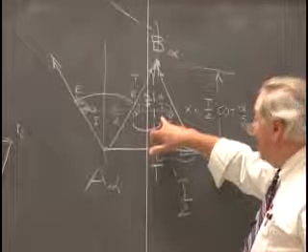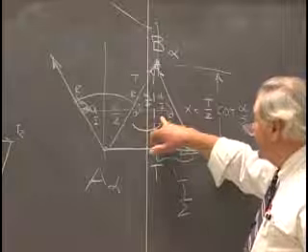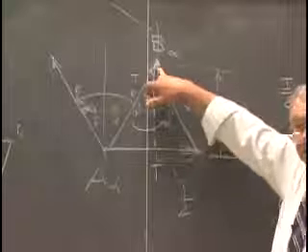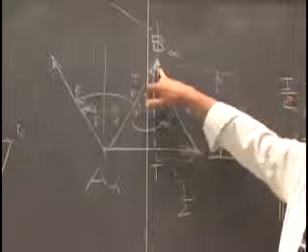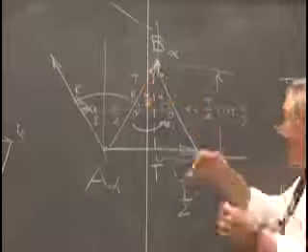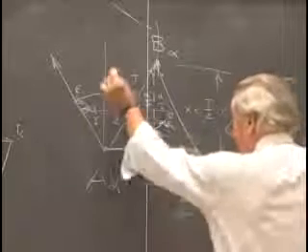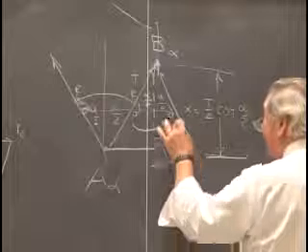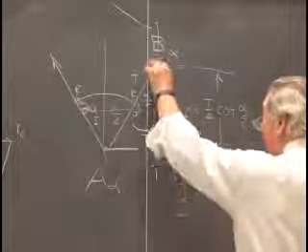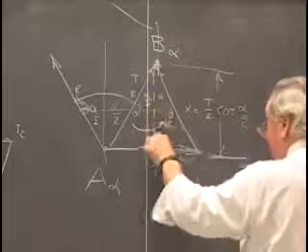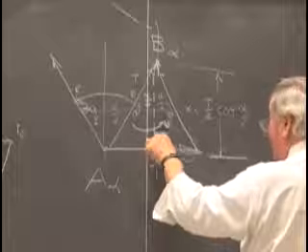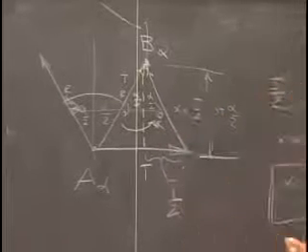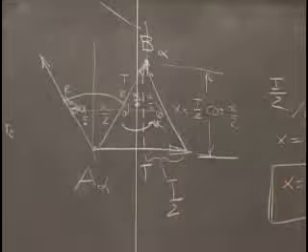If we ask what is the locus about which this rotation has occurred, we use the fact that the locus of a rotation axis is the only point that's left unmoved by the net transformation, and the place where this translation intersects the translation that has been shifted over by t is a point that sits up along the perpendicular bisector of the translation by a distance t over 2 times the cotangent of alpha over 2. So that's in the abstract.